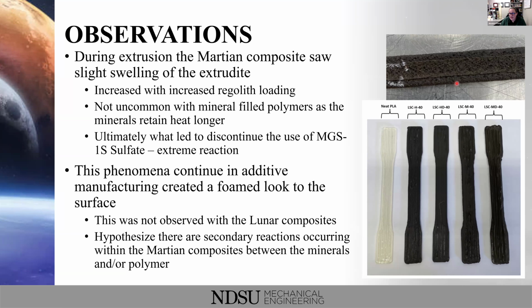So this top picture up here is a Martian part, and you can see the surface of this part is very, very pitted. And that all occurred in the additive manufacturing process, right? So when we extruded it out and laid down those layers, it was very, very foamy, which we think is impacting the mechanical properties. And so we think if we can reduce the foaming effect and create a smoother surface finish on these parts, we can get better mechanical properties in the end, which would make these even more viable materials when we're thinking about producing parts on the Martian or the lunar surface.